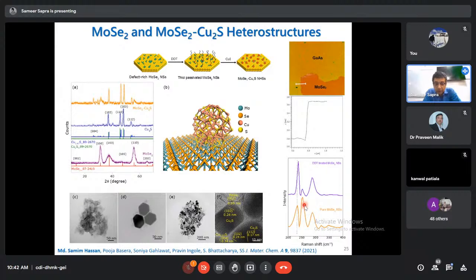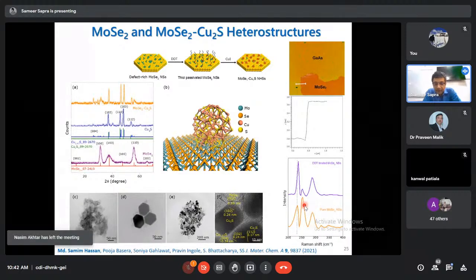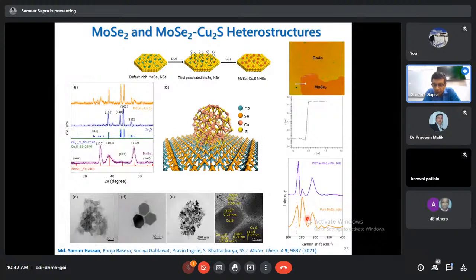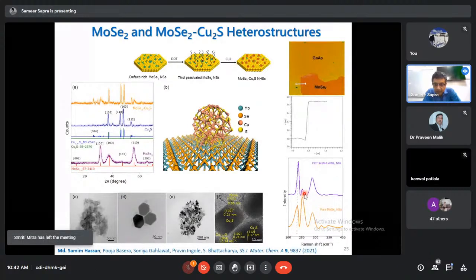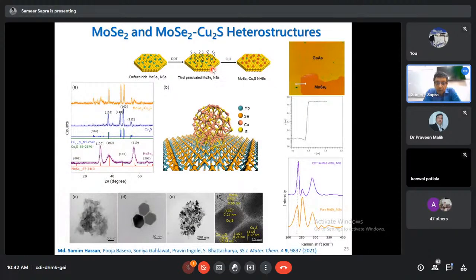You'll never see this mode when you make CVD-grown molybdenum selenide, sulfide, whatever. Well, sulfide depositions would be different, but selenide. But when you treat this with DDT, the intensity of this defect mode goes down drastically, telling you that your defects have been passivated. Okay, and on top of that, if you're going to throw some cuprous iodide, it's going to form these cuprous sulfide particles on top of molybdenum selenide, and these are attached over here very nicely.